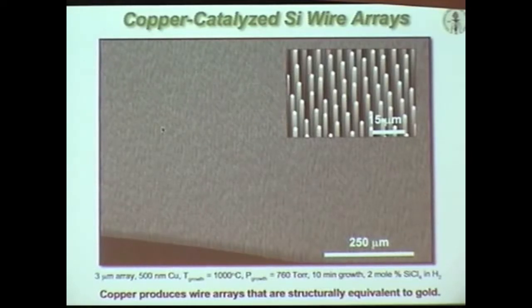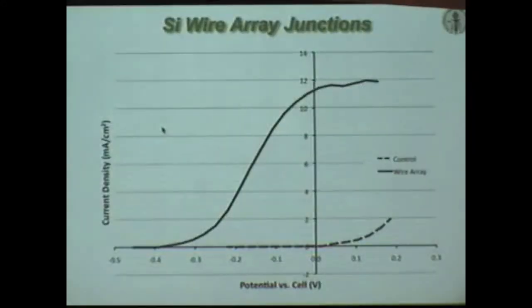But in fact, the solubility limit of gold, nickel, and copper in silicon is, even still, with a deep level trap, enough to give you a 2 nanosecond lifetime, which is a 2 micron diffusion length. And these rods are only 4 microns in diameter, and so we should be able to collect them all. Okay? So this is really rotten silicon, which we can just thermally refine and purify, but we don't need to. And indeed, it works pretty well.